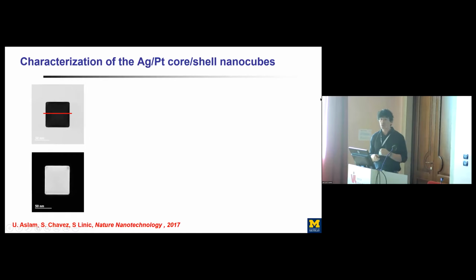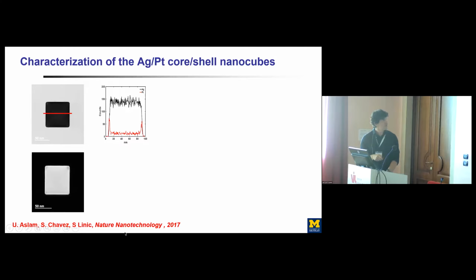It took us a very long time to fabricate a nice system where you have a large silver core and then cover it with a very thin shell of platinum. And here I show some of the elemental mapping of this silver platinum core shell particle. You can see here platinum nicely identified. Here you have the silver core, and then you have platinum on the edges of this nanoparticle.